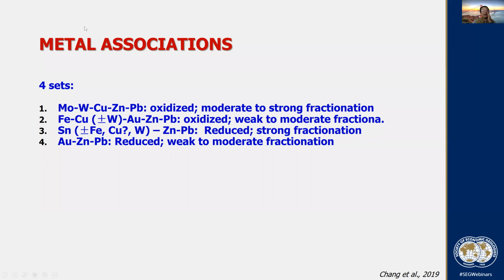Okay, so based on that, we can have metal association of 4 sets. If it is oxidized and moderate to strong fractionation, we have moly, tungsten, copper, zinc, lead. If it is still oxide but weak fractionation, then we start to have more iron, and no moly but more iron, and we can have more gold, not moly. And zinc lead is here all the time. Reduced intrusion, strong fractionation, we will have tin closer to the intrusion, zinc lead again further out. And reduced intrusion to moderate sites of association, depends on the magma.